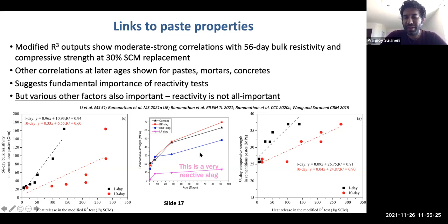Now, the reason for that is very simple. In this slag, we have melilite, which is a phase that reacts very rapidly, but it actually messes up cement hydration because it interferes with the sulfate demand. It interferes with the alumina-silica sulfate balance. So this slag is reactive on its own, but it does bad things to the cement hydration.